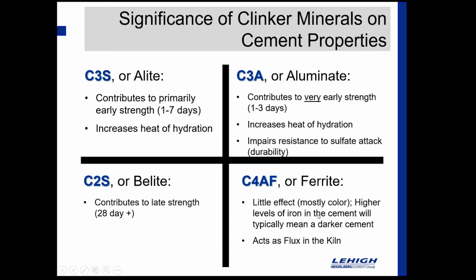And so C4AF, or ferrite, has little effect overall, but it does affect the color. So if you see a mill test that has an abnormal, high iron content, that would mean you're probably going to see a darker cement. If you've seen some cements that are very dark, that means they've got a lot of iron. If they're really on the light side, they might not have as much iron. But from a production standpoint, the ferrite does have a role in the kiln as it acts like a flux and helps everything to melt a little more efficiently and more completely. So that helps the overall clinker mineral composition performance.